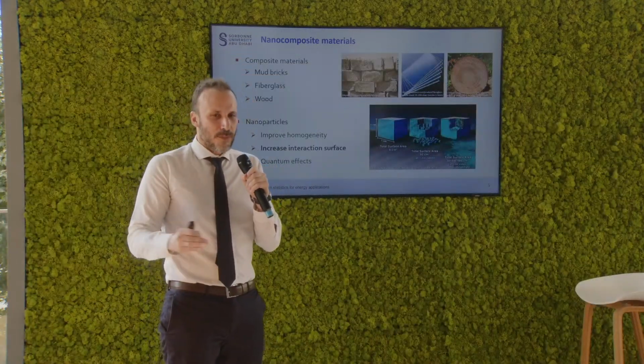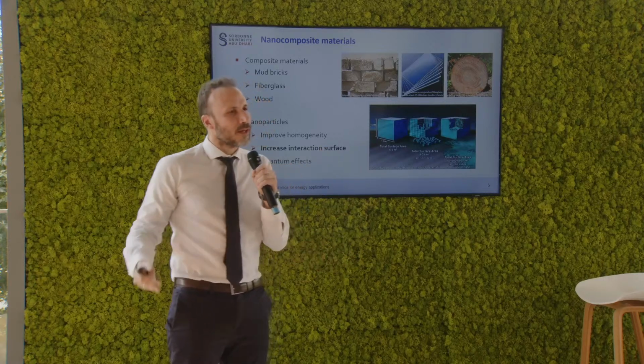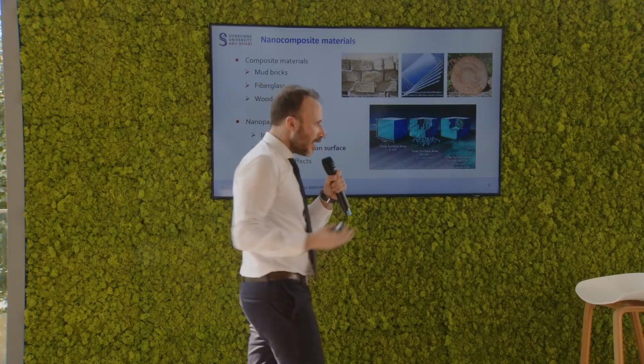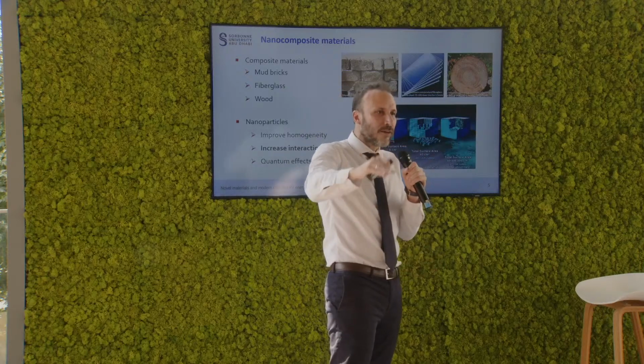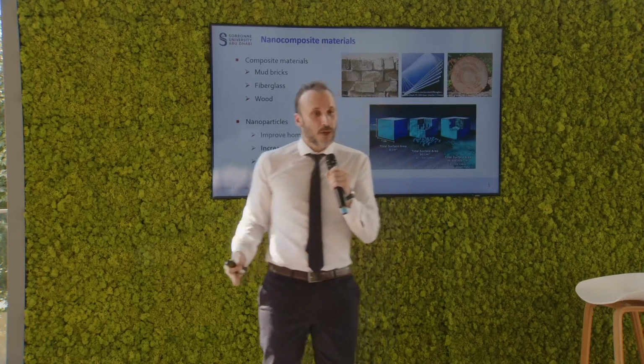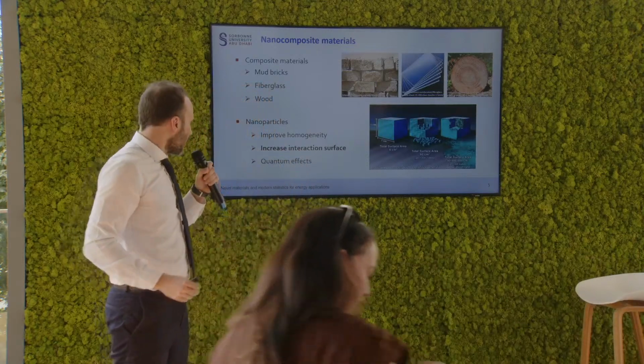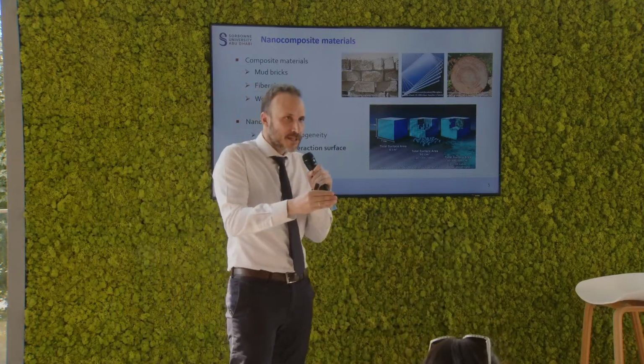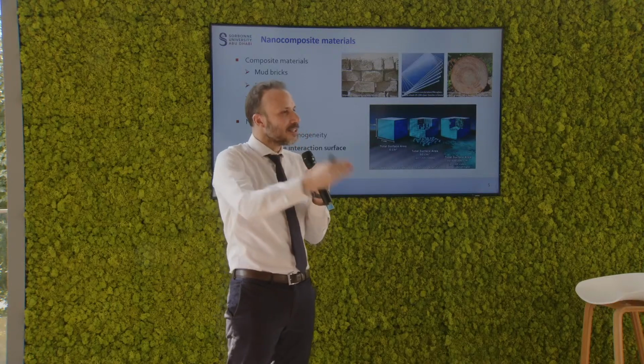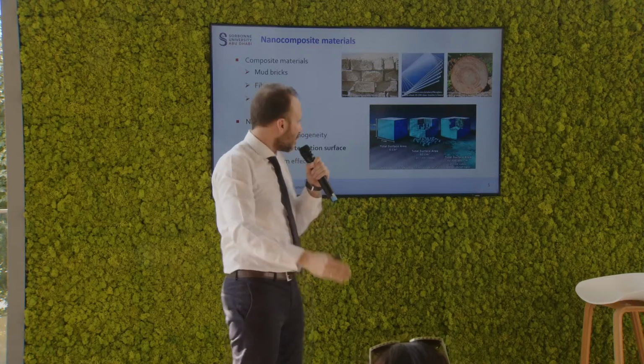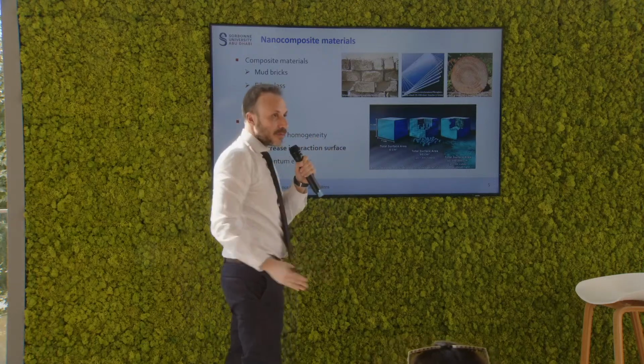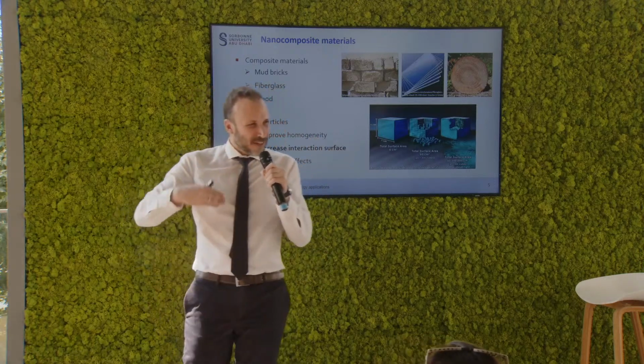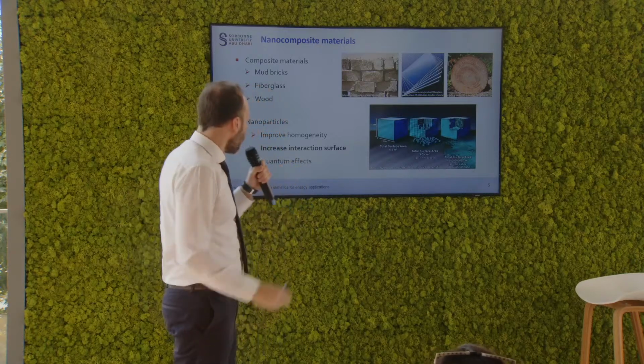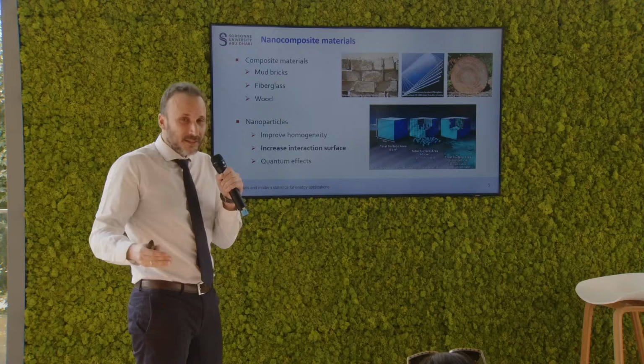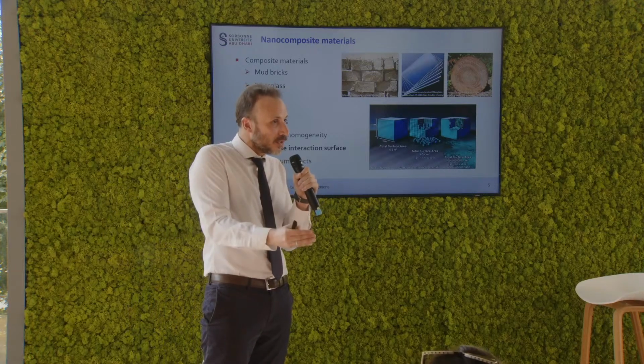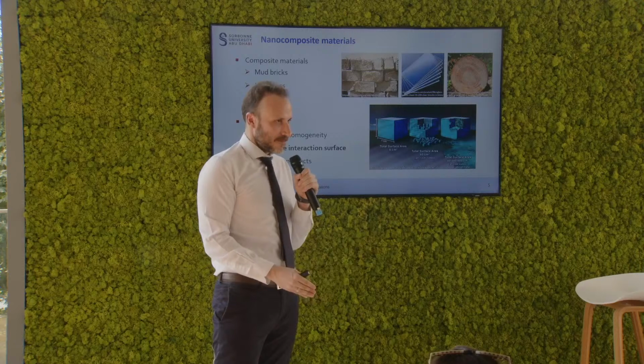The interaction surface is basically this: when you use an active material, all the phenomena that you're going to actually observe appear most of the time on a particular surface of that active material. So the bigger surface you have, the better that is. Now, if you have a certain amount of active substance and you start chopping it down, you are essentially creating more and more surface, which means if you go to the very small region of nanoparticles, in the nanoscale region, you have effectively created a huge amount of interaction surface, which means that you have created a material which is much more efficient with a much smaller initial substance.